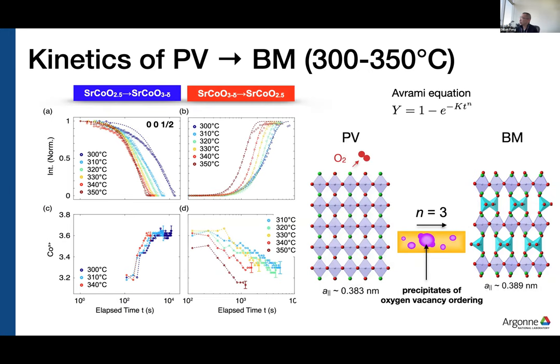Now, when you switch back to the Brownmillerite phase and you switch back to nitrogen, this has an N of three, meaning a three-dimensional process. And one can sort of rationalize this by saying, okay, it doesn't have to start at the top and move down to the bottom. It's really just an ordering problem. So you have a lot of oxygen vacancies. What you really need to do is create a nucleus of Brownmillerite where the oxygen vacancies are ordered. And then you can propagate from that. So it's a 3D nucleation problem. And so this is what I'm trying to draw in this schematic over here.